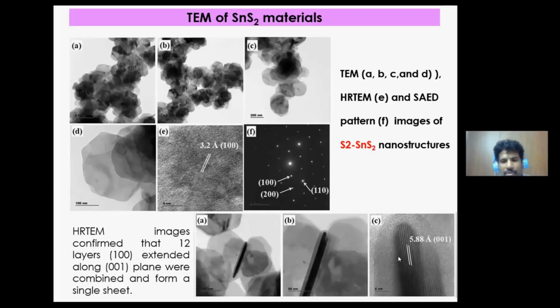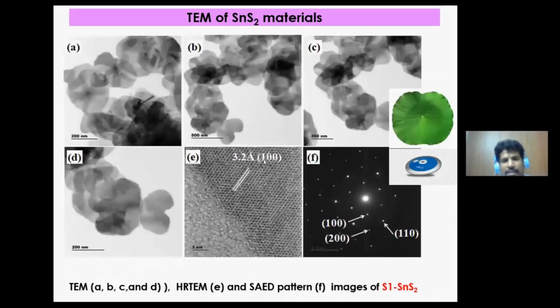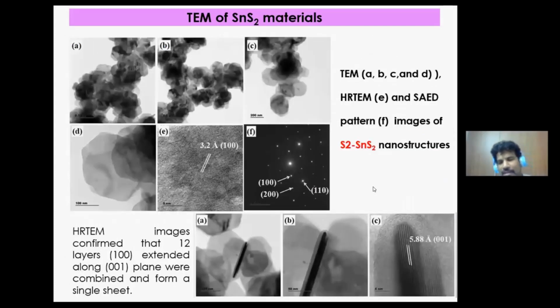Accidentally, we got a chance to take the side view of this material. So we measured the plane, that is the 001 plane, which means the 100 plane is extended along the 001 plane. We got a very flat nature of the material. In the case of S0, S1, S2, we don't get any side view of the material, but in the case of S2, SnS2, we got a side view.